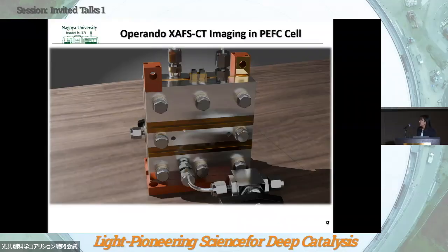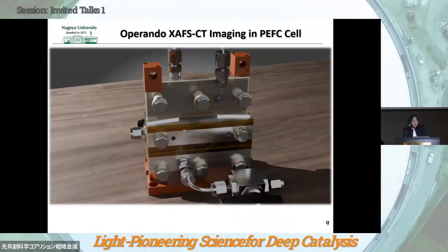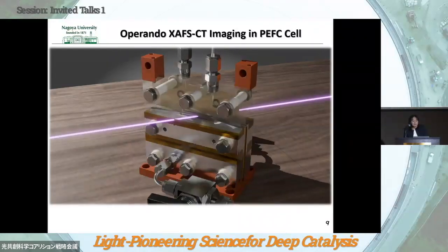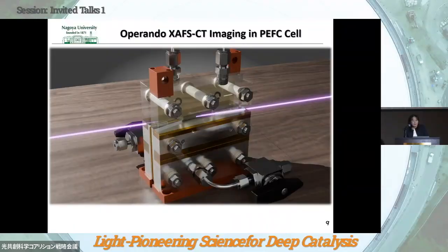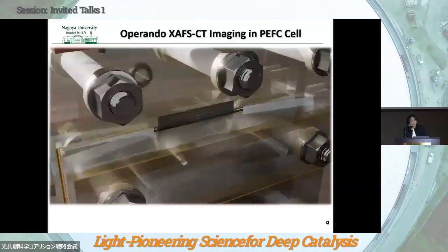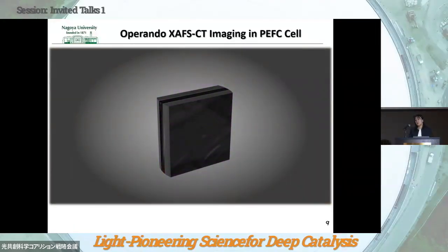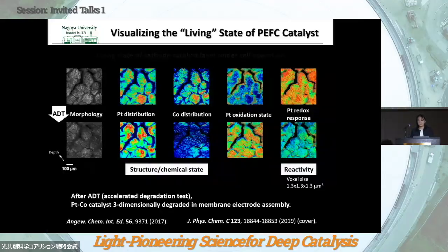So we have developed the operando XAFS CT imaging cell, which is a type of standard cell for PEFC systems, and we prepared a window for X-ray imaging. We irradiated hard X-rays to the sample under the working condition, and recorded the two-dimensional spectra on the catalyst layer. After the reconstruction process, we can get a three-dimensional image of a particular area in the membrane electrode assembly under the working conditions.